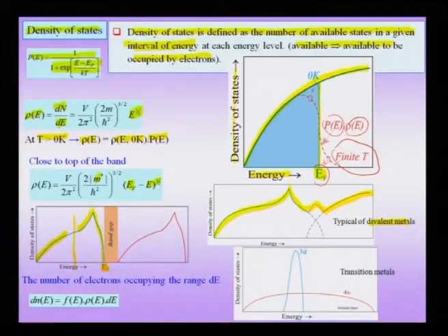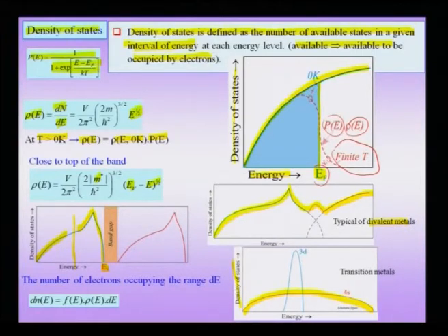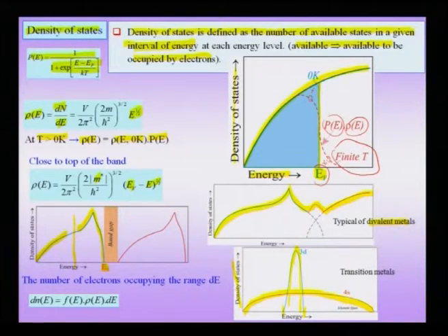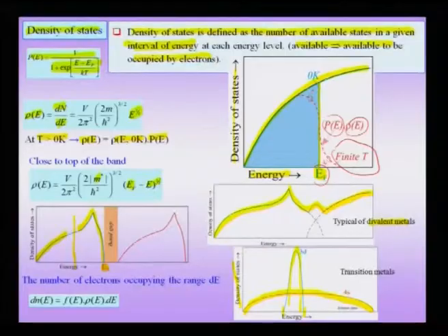This is typical of divalent metals, and the diagram corresponds more closely to transition metals like iron. In transition metals, the 4s band, which is a broad band in density of states, fills parallely with the 3d band, which has a high density of states localized to a small region in energy. This has important implications: the 3d band is highly localized as a narrow bandwidth, which tells us that the 3d electrons are not fully itinerant — they have a partial localization character. Later on, we will see that this plays a very important role in the magnetism of iron.